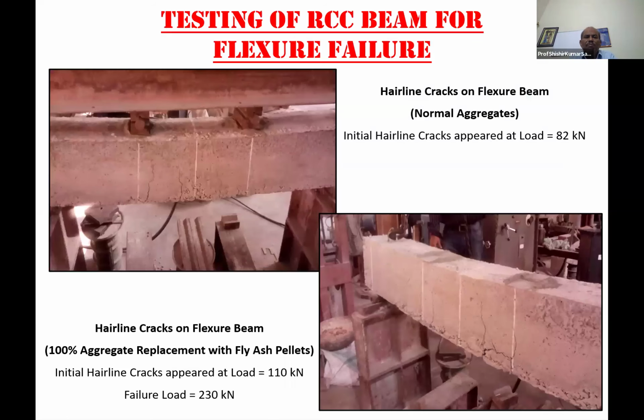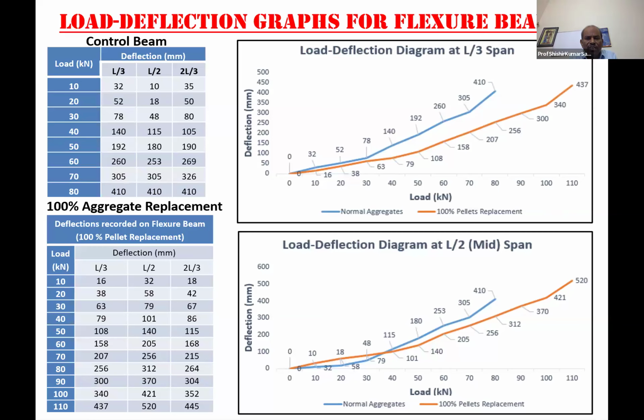Then testing of RCC beam for flexure. Here we have seen hairline cracks on the flexural beam. This is a 100% aggregate replacement with fly ash pellets. This one is normal aggregate. This bottom one is with fly ash pellets. What did we see as the difference? Initial hairline cracks appeared, but the failure loads are also different, but comparable. Load deflection curve.